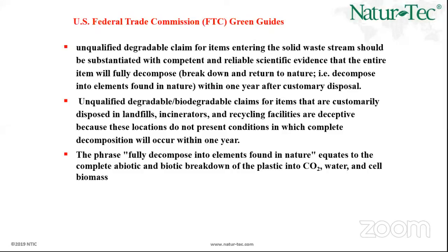There are lots of reports in the market where people talk about, let's say they run the study for 15 days and they say that 10% or 20% of my material is biodegraded. And so in the next 180 days, 90% would be biodegraded. So they do an extrapolation, which is not correct. We cannot extrapolate a microbial assimilation mechanism because it's not a linear mechanism. The way microbes consume a food source, or consume the carbon in the food source, is a completely different mechanism. It cannot be plotted in a certain pattern. It cannot be a linear pattern or a parabolic pattern or an exponential pattern.